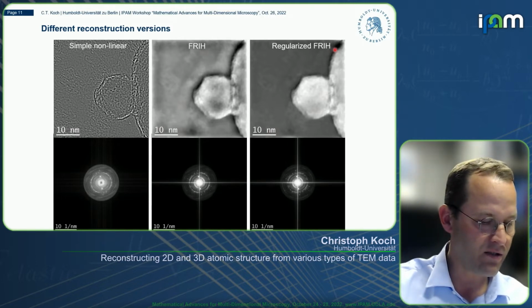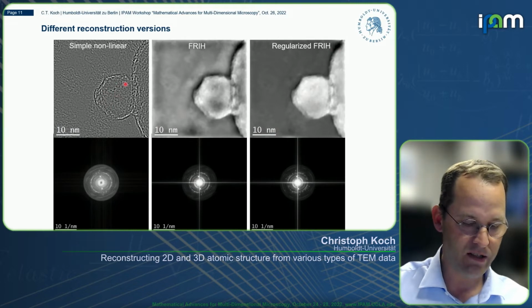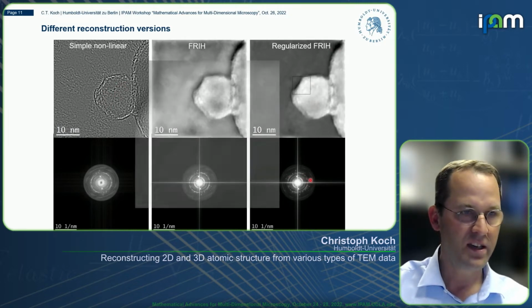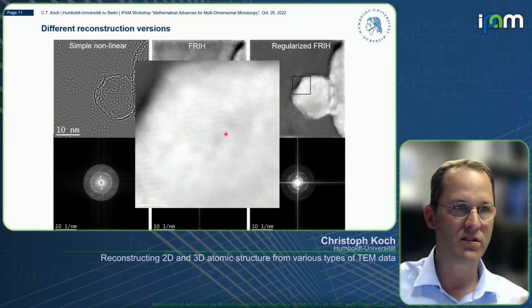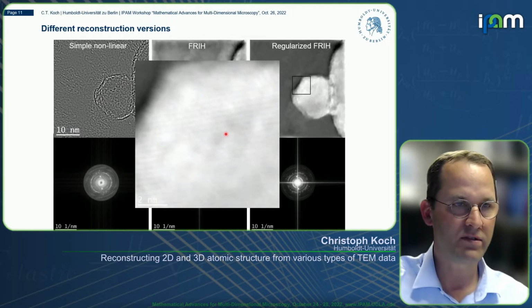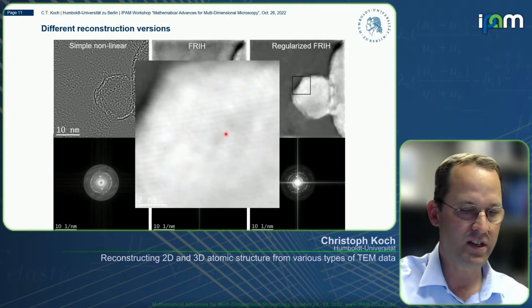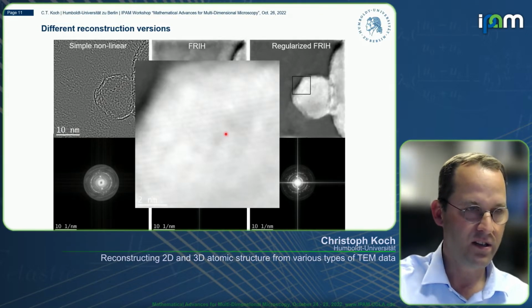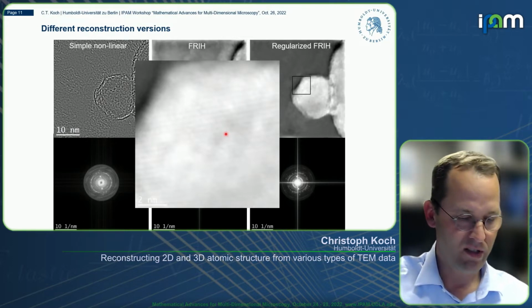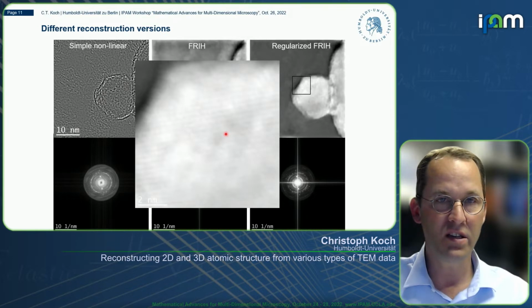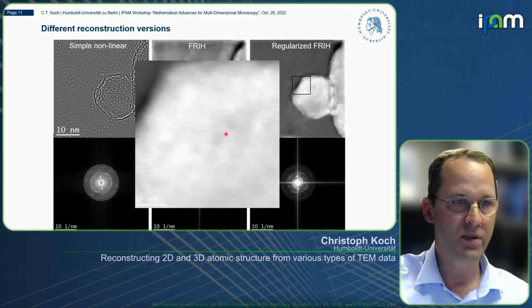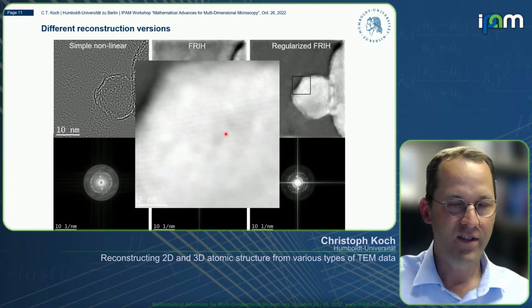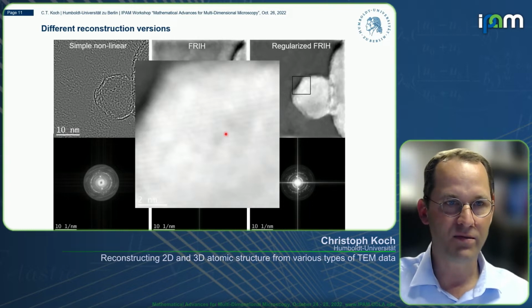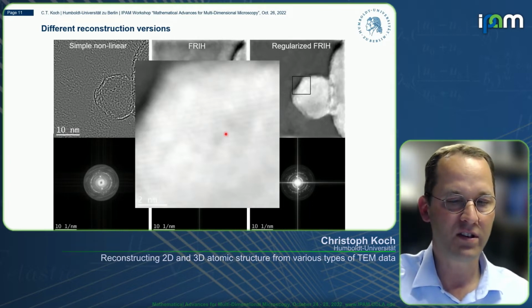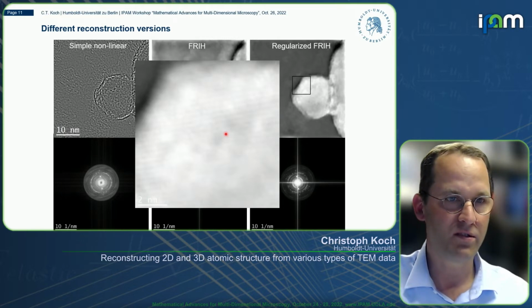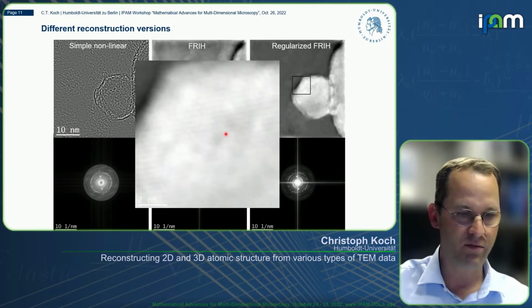And the lattice planes that you saw in the original reconstruction, if you look at the FFT, they're still there. And you can also see them in the image. It's just that because you now recover all the information, you have a realistic balance of the high and the low spatial frequencies. You really need to adjust your contrast in order to see them better. But that is a more truthful reconstruction, because you now have all the information. It's always a question whether you want all the information or whether you want to highlight certain information. At least from my perspective, it's not the task of the algorithm to decide, but you can afterwards do some high-pass filtering of the reconstruction to get what you want. Or maybe you want a low-pass filtered reconstruction in order to recover other information that you might have been after.